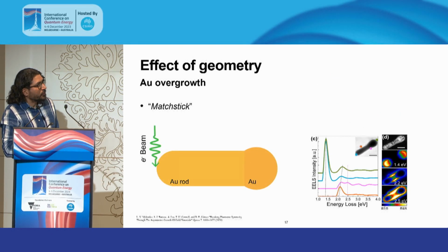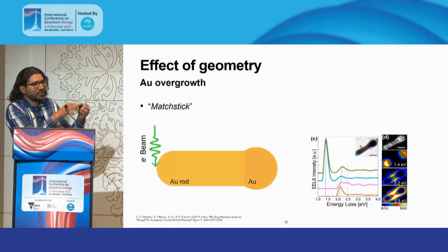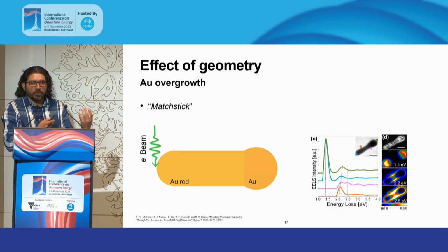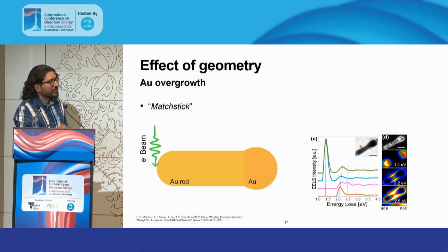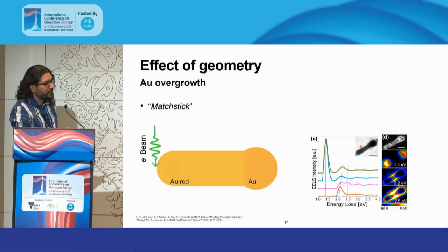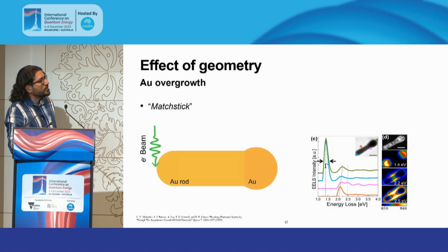As a further control, we grow gold on gold to achieve the same geometry as our target structure, just to test if the geometry plays a critical role in the process of damping. We get the same sort of set of data. From this data, we again get the line width.